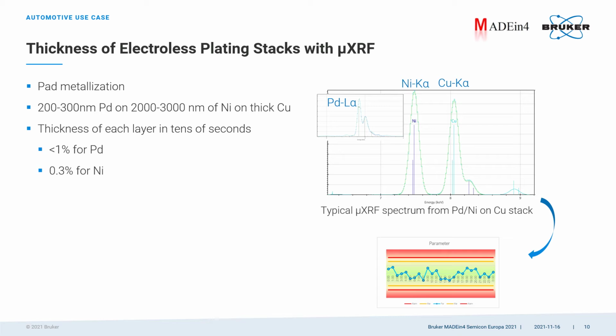Another example shown here. Electroless plating stacks are used in power chips, especially for automotive. These metal pads are a few hundreds of nanometers of palladium on a few thousands nanometers of nickel on thick copper. And sometimes this is then topped by a thin layer of gold. It's important to monitor the thickness of each film in the stack. With micro XRF you can do that in tens of seconds, in line and on product wafers.